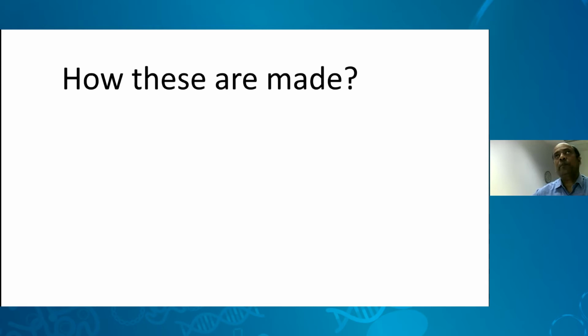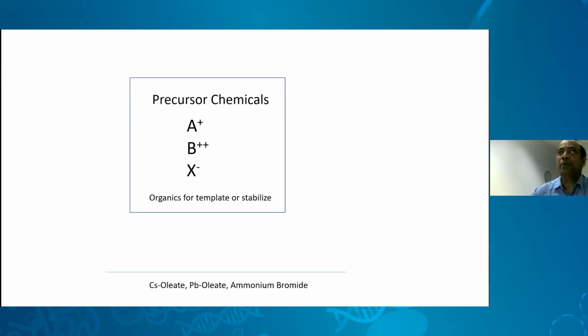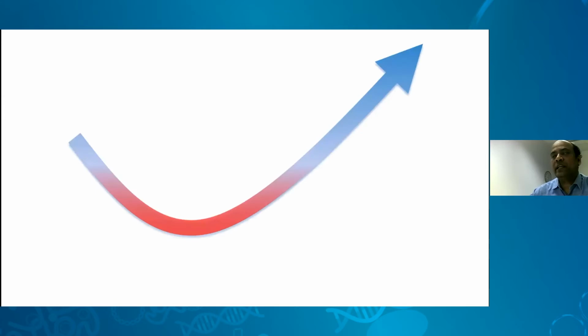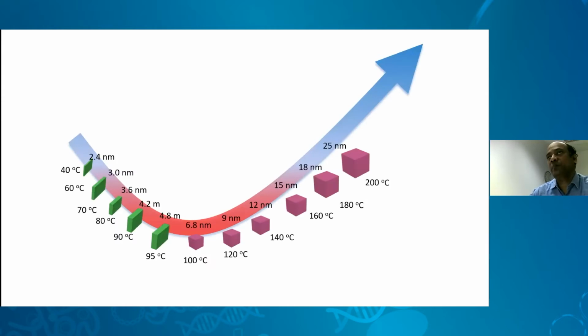So now the question comes to the point of how these are made. If you go for the synthesis of these ABX type of materials, you have to have 3 types of precursors together. One short example I'm giving here: these 3 precursors, cesium, lead, and bromine, we mix together at room temperature and inject at different temperatures. Once we inject at different temperatures in the reaction flask, it starts from 2.4 nanometer and continues to 25 nanometer. There are platelets with tunable size and thickness, and you could see here the cubes, whose size is also tunable.